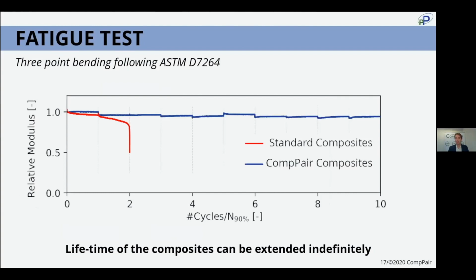Here, what you have seen is a demonstration of static damage and repair of those damage typically after an impact. However, into typical application, what you would find is fatigue damage, so cracks that are growing over the time due to the different stresses that are applied onto those structures. We have tried and we have done the reproduction of those cases, exactly that onto some tests.